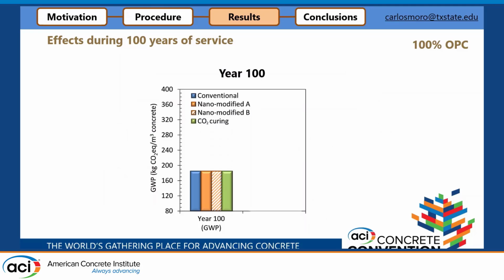So, as an overview, at year 100, considering the traditional methods, we will have the same exact value. And using this dynamic methodology, different concretes will have different ones. For example, one thing that we can focus on is that even though the CO2 curing had lower CO2 emissions at the beginning, nano-modified A had lower final CO2 emissions. So accelerating the CO2 uptake during the service life can really make an impact at the end of the service life.